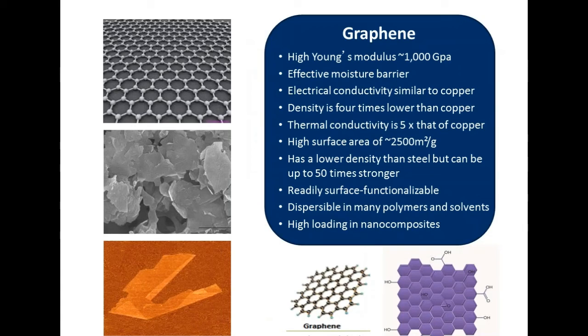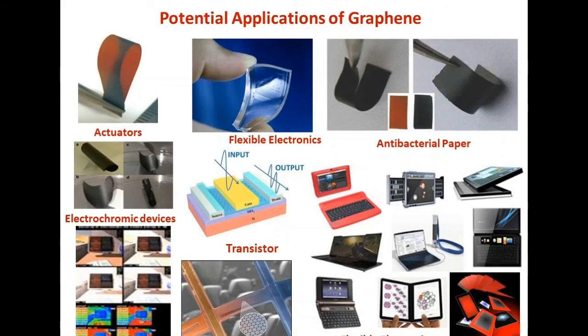The nanomaterial has effective thermomechanical, but more importantly, thermal and electrical conductivity properties similar to copper. On the other hand, by modifying it using an exfoliation method to solubilize it, one can produce graphene oxide, which is essentially a graphene with a lot of carboxylic, epoxide and hydroxyl groups, products of the oxidation method.